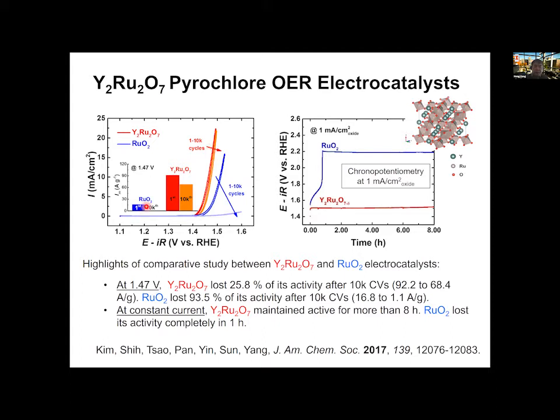The reference ruthenium oxide system drops quite dramatically. And you can also look at the potentials at the relatively low current densities, and they maintain fairly well. So this is one system we work on.